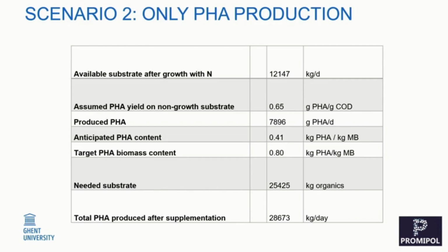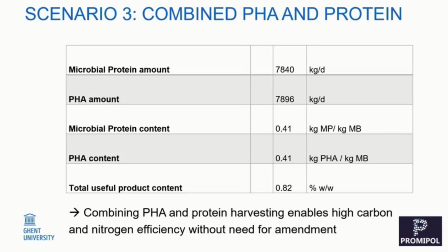If you do that, then with a typical stream there, you're only going to have about 40% of the cells containing your bioplastic. But you want 80% in order to have a good production process. So what you have to do is throw in about 25 tons of additional organic matter in order to have more bioplastics, wherever you get it. So whichever route you choose, if you choose one product, you end up with a situation where you have to amend the wastewater, or you end up with a low yield or a low content of product.